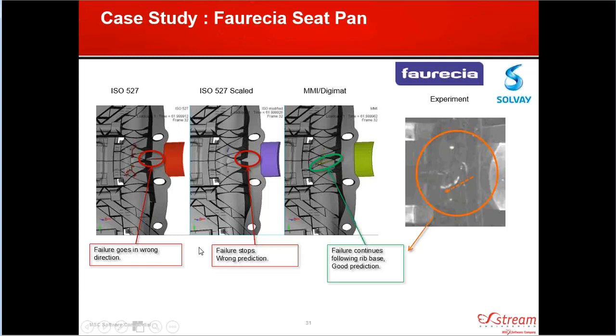In the scaled approach, we finally started to have failure at the rib, but it's too late in the analysis. And in the Digimat approach, we had failure happen in the right place at the right time, and now it's progressing in the right direction along that rib to match what we actually saw in the test results, or experimental results.